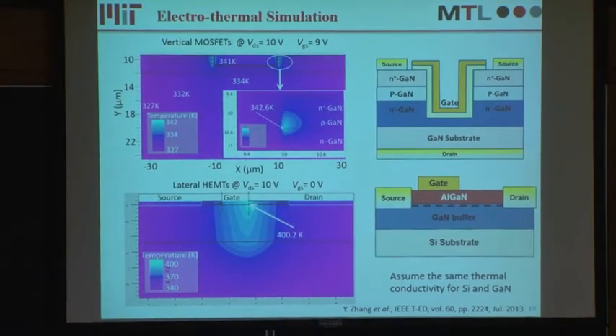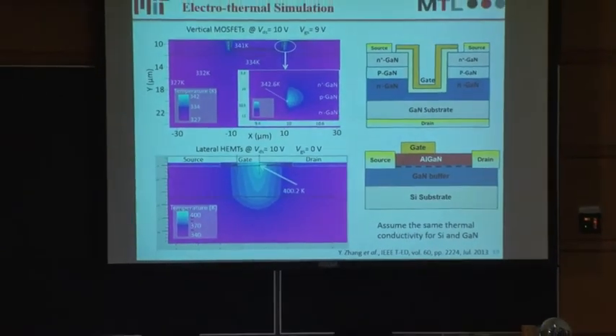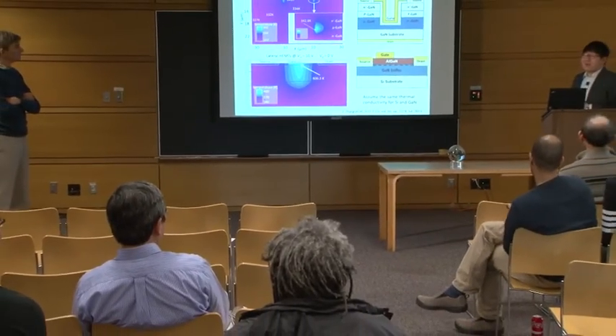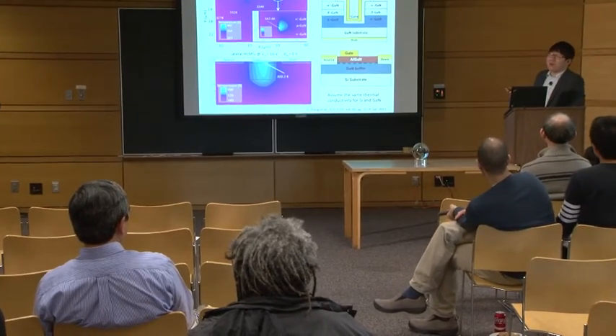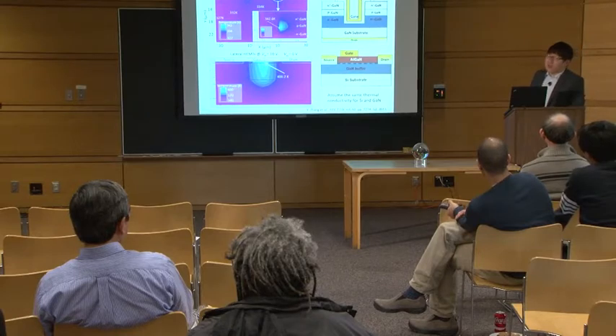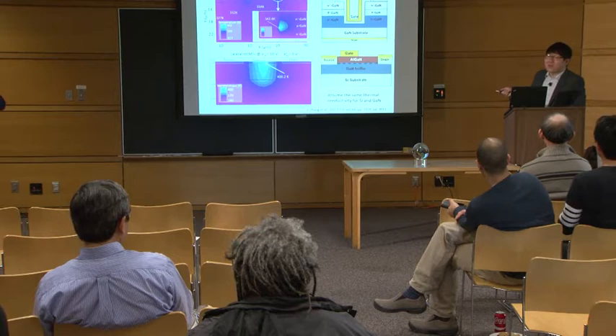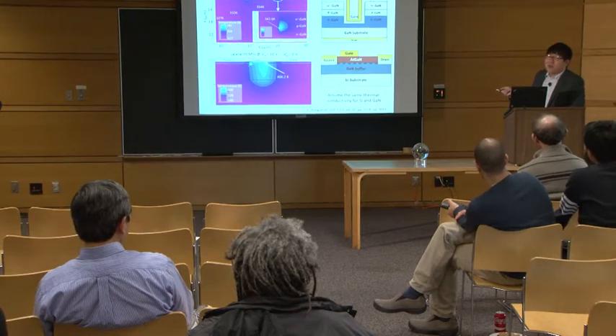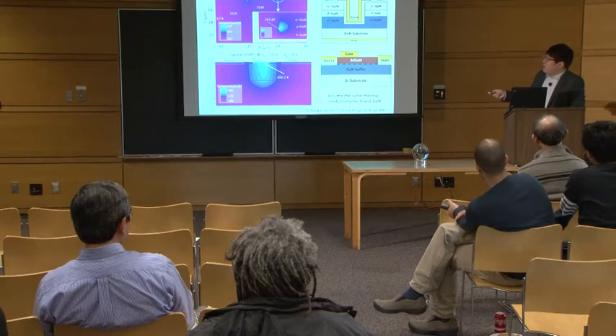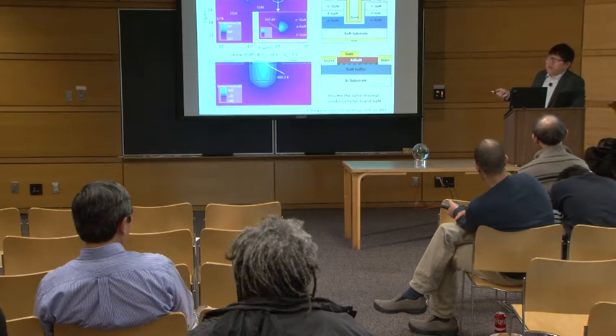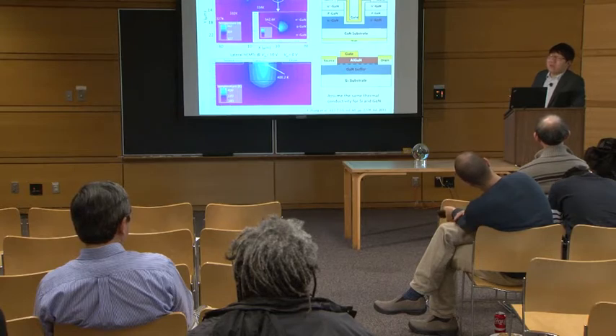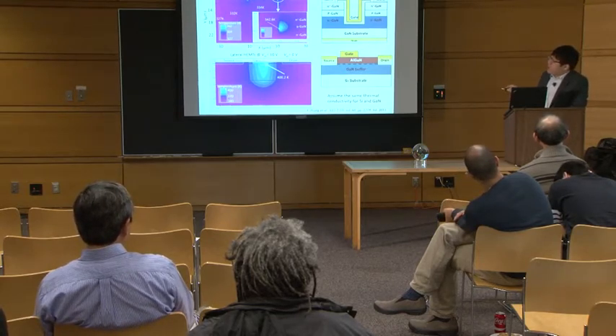Is there a fundamental reason heat cannot be extracted from the top? I think people are also trying to develop methods to extract heat from the top using new package schemes. But I think the main challenge, especially for the lateral device - for the vertical device it's totally possible, but for the lateral device, because the 2DEG channel is very close to the surface, even with passivation layers, anything that changes the stress of this 2DEG region will significantly change device performance. So that's the main obstacle to extracting heat from the top for lateral devices. For vertical devices, it will be much easier.